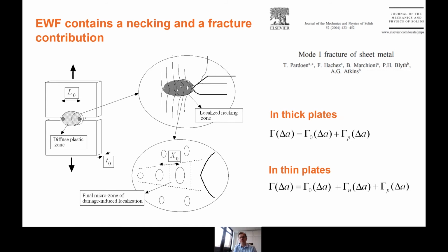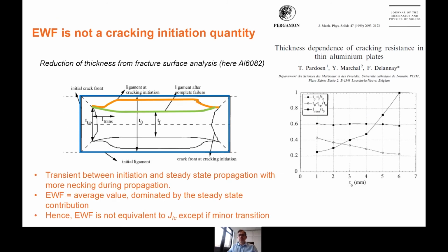And this is very important because that is the origin for which there will be a thickness effect. That is the origin of, most of the time, a larger fracture toughness in the plane stress regime compared to the plane strain regime. And it's also probably most of the reason for which there is a difference between cracking initiation toughness and crack propagation. So let me go to this question of crack propagation versus cracking initiation resistance for the essential work of fracture.